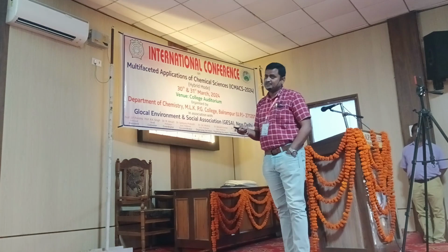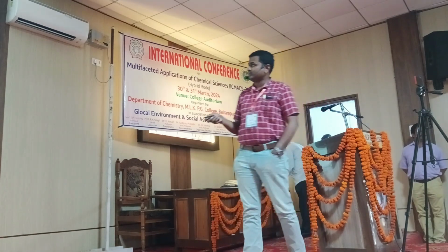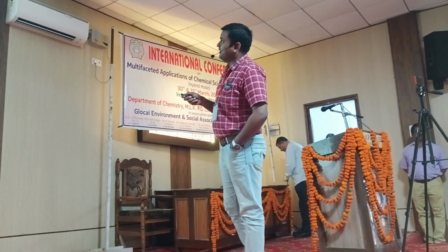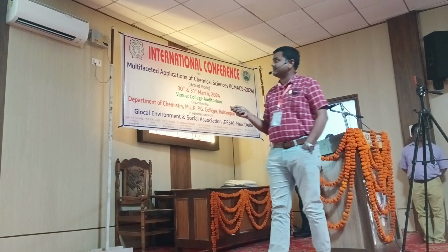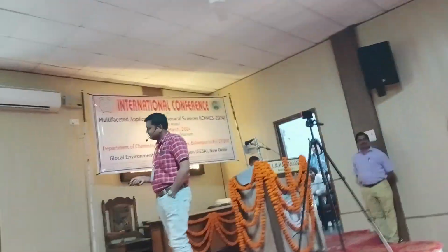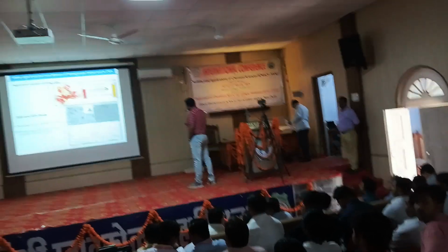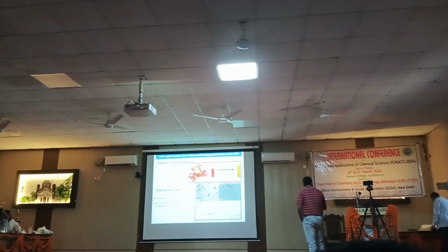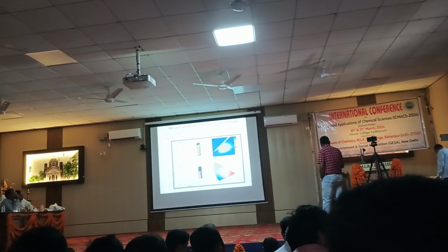In the second line of work, which is my PhD work, we also prepared white light emission from the mixture of pomegranate extract and its carbon nanoparticles, and this was published in the Journal of Materials Chemistry C. We prepared green emitting carbon nanomaterials from pomegranate extract by hydrothermal treatment at 140 degrees centigrade for 24 hours, and then after centrifugation we found the yellow emitting carbon